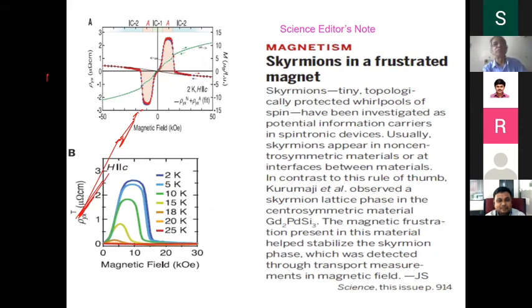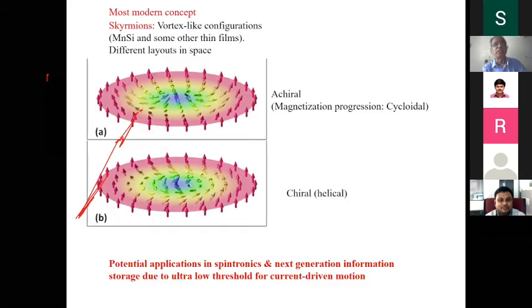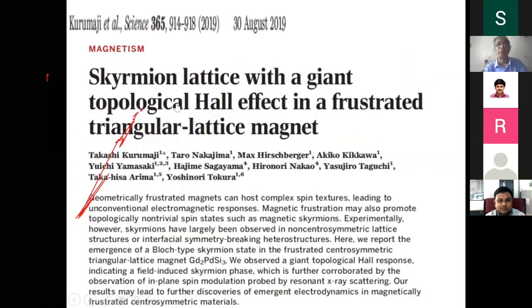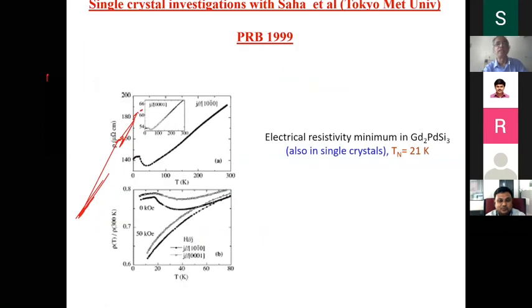Basically, you see a spin, we call spin textures. You could see very funny textures or orientation of spin, so they're called skyrmions, a new concept in magnetism, which is evolving now, and there are potential applications for next generation information storage. So this material, the 4f electrons, is considered to be an example for skyrmion, and we reported even 2 decades ago, even before the phenomenon was discovered. That time we did not understand. Of course, the group doesn't give credit to us, that doesn't matter, but we are happy to see that the same feature was reported by us 2 decades ago.